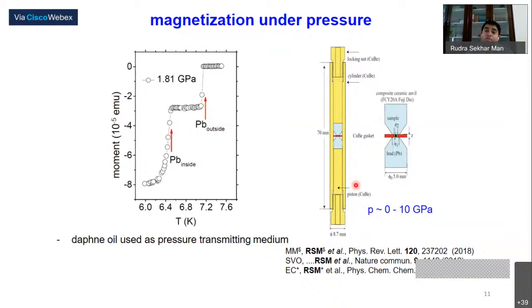These things also give you the background, because your sample is sitting just at the center here, but the whole pressure cell is inside. I mean, you are also measuring the whole pressure cell. So you have to choose the material of the pressure cell in such a way that your background noise is very much less, otherwise you don't get the signal from your sample. But if your sample has a huge signal, then you forget all these issues.